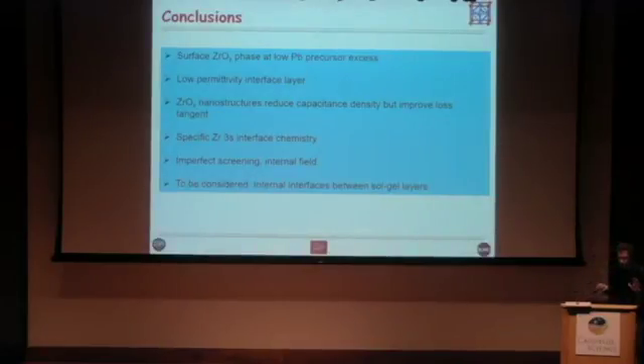So I'll conclude there. Just to remind you, we looked at the sol-gel PZT layers. Depending on the lead excess, there can be a low dielectric layer based on zirconium oxide. This layer reduces the capacitance density, and it improves the loss tangent, but it reduces also the breakdown voltage. There's a specific interface chemistry. The screening, despite the solid electrode, is imperfect, and this gives rise to an internal field. There's one thing we haven't considered in these technological samples: the sol-gel is grown layer by layer, and we haven't considered what happens at the interface between these layers, which is probably an important point.